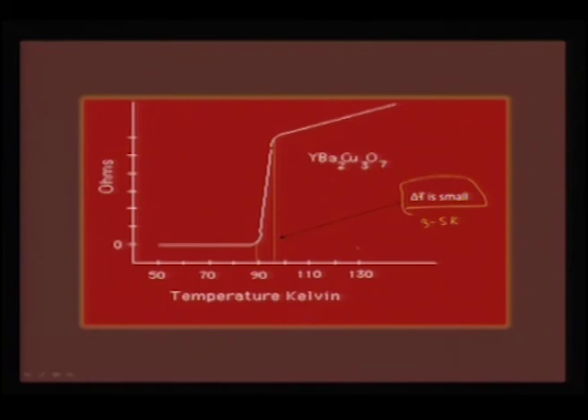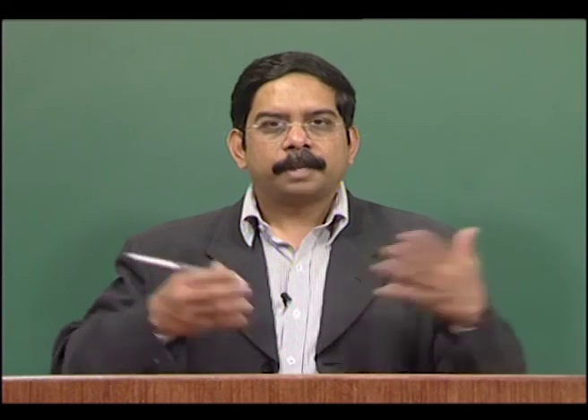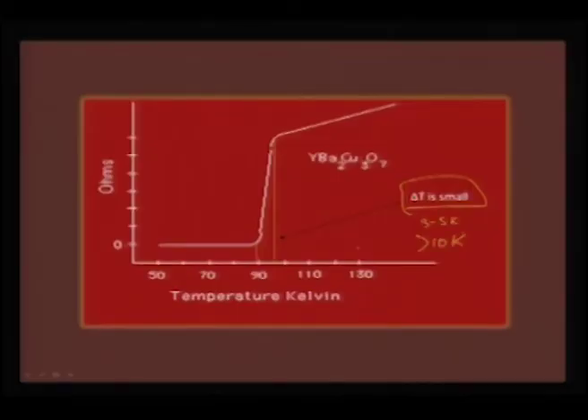You would also find that if there is a biphasic compound or some impurities, delta T can be more than 10 K, which clearly indicates that there is an insulating phase present in the compound. So, what is the phenomenon of high Tc, and what do we learn from here?